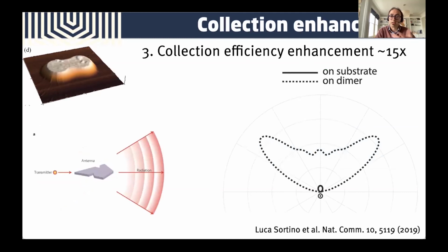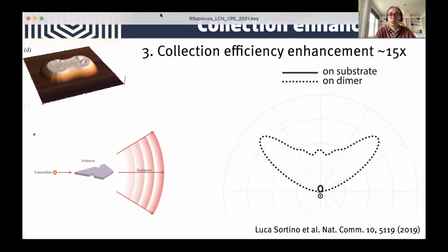Then we also extract the light more efficiently with the antenna. So this is the reverse effect. Now the emitter, the WS2, emits the light, the light is coupled to the antenna, and the antenna radiates the light out of the sample. You see here on the plot on the right that if I don't use the antenna, I have the black line, the very little circle. But when I use the dimer as an antenna, then the intensity, this is a polar plot, is a lot brighter, and it is now directed outside of the sample, which is the side where we can collect. And so in this way, we get another 15 times enhancement in collection.